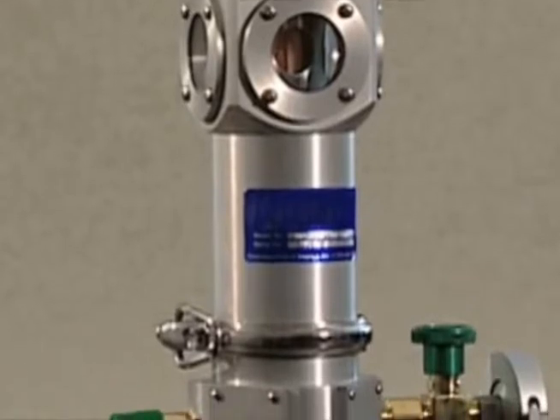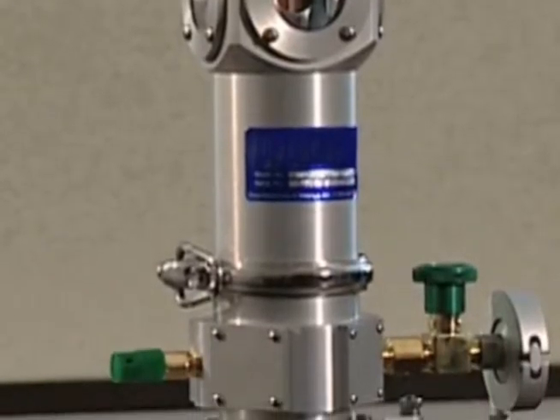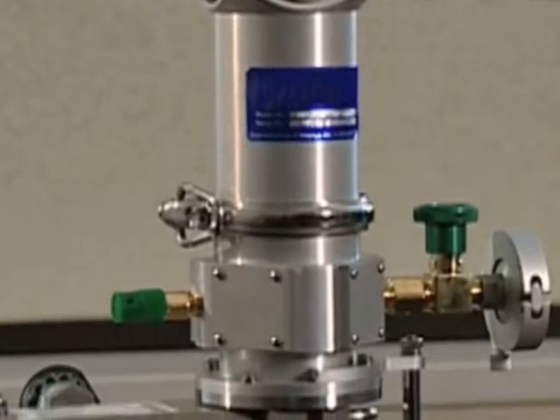I think what I learned in doing my investigation is that there's not a lot of information in the literature on low temperature spectroscopic properties. In order to be able to make the laser, you need to know certain things. The wavelength of the transition that you're looking for, where you absorb and where the laser operates. You need to know what the emission cross-section is, the so-called laser gain parameter. And you also need to know how the lines broaden and narrow with temperature.